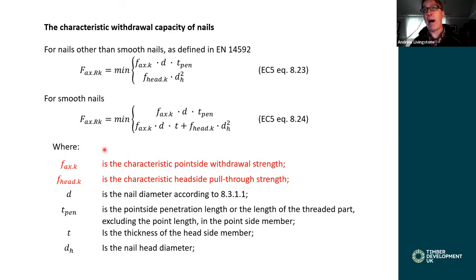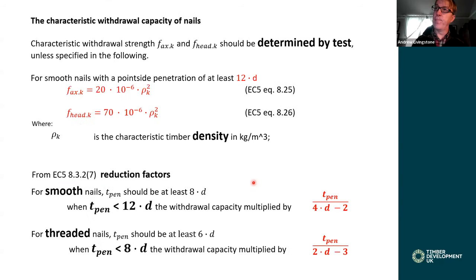Now, the characteristic withdrawal capacity of the dowels is essentially the axial withdrawal of a fastener, or the head side pull through of a fastener. We've got two examples here, for smooth nails, and for nails or dowel-type fasteners other than smooth nails. We still have, however, to get the characteristic point side withdrawal strength and the characteristic head side pull through strength. These should be determined by test. However, we can calculate it, or not calculate, predict, as long as these following criteria are met.